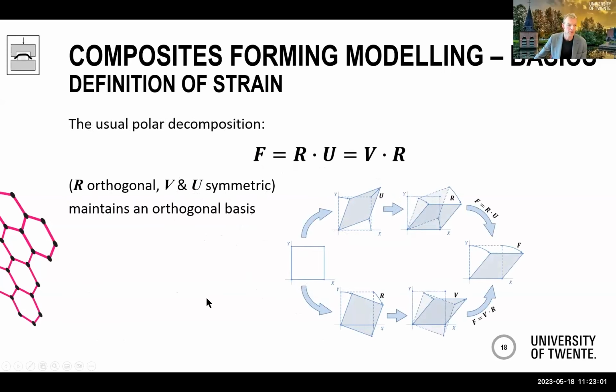And usually one would use a polar decomposition with a right stretch tensor U or a left stretch tensor V, and these two are both symmetric, and this R is a nice orthogonal, let's say a rotation tensor, and this nicely maintains an orthogonal basis. So either you first deform with U, and then you rotate it to get your deformed situation, or you first rotate, and then you deform it with V, and you get your deformed shape. Both ways lead to the same result, more or less. And the nasty thing is that this retains an orthogonal basis. And in composites forming, that's usually wrong because we can have significant shear deformation, which makes it non-orthogonal in the end.